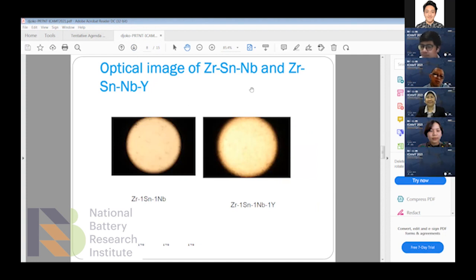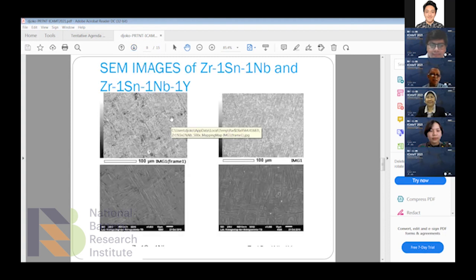This is the optical microscope image of the two alloys. If we look, it consists of parallel plates and basket-weave microstructure, and we see it more clearly by SEM. This is the SEM image of the microstructure of the alloy, with parallel plates and basket-weave for zirconium, stannum, and niobium. This is 100 micrometer, and this is 1000 times magnification. And this alloy has yttrium added. This is the microstructure of the alloy at 100 micrometer and 1000 magnification. If we look more clearly, there are parallel plates and basket-weave microstructure.